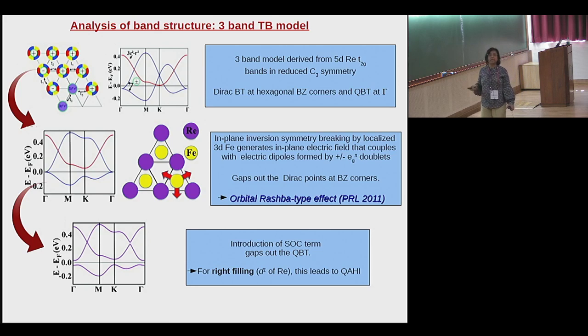You can start with a 3-band model of rhenium t2g. And if you put that on this buckled honeycomb lattice, what you get is a Dirac band touching at the Brillouin zone corners, which is the hexagonal Brillouin zone shown here, and a quadratic band touching at the gamma. So you have a Dirac-like band touching here and a quadratic band touching there.